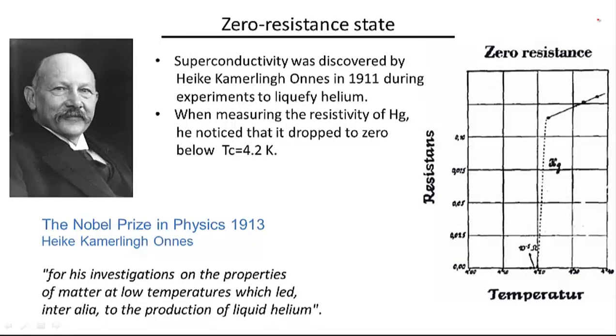To do so, let me go back in time a little more than 100 years ago, to 1911, when this happy-looking guy, Heike Kamerlingh-Onnes, was performing various low-temperature experiments to liquefy helium. During these experiments, he noticed that the resistivity of mercury dropped exactly to zero below a certain critical temperature of 4.2 Kelvin. This was very surprising, and actually it is very surprising.